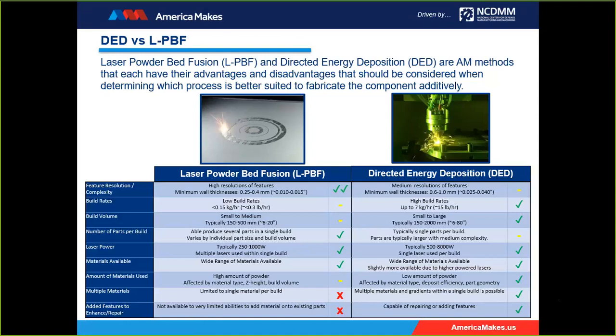Starting with the feature resolution and part complexity, laser powder bed certainly has its advantage in terms of wall thicknesses, surface roughness, and resolution. The laser beam spot size is typically in the 20 to 100 micron range. The slight trade-off with that technology is support structures are needed for overhang angles, usually less than 45 degrees as a standard rule of thumb. DED is a near net shape that will not achieve the same level of resolution compared to laser powder bed. The beam spot size in DED is typically 500 to 600 micron in diameter at the minimum, but usually hovers around 1 millimeter. It can, however, utilize 5 or 6 axis motion to produce parts without the need for support structures.